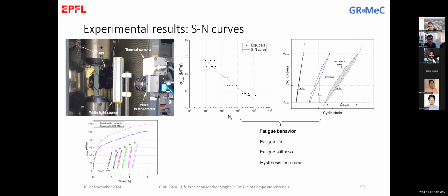So to avoid this, you can do two things. Either you test at very low frequencies, so you have to test the specimen at 1 or 2 hertz, which takes ages to finish your testing. Or, as an alternative, you try to cool down the specimen somehow. And in this case, we found these methods with the chamber and the additional fan that seems to work quite well.